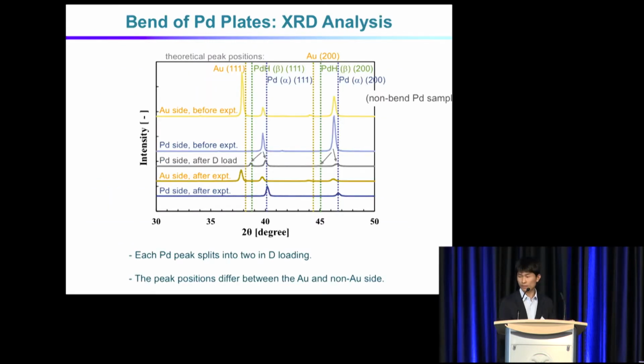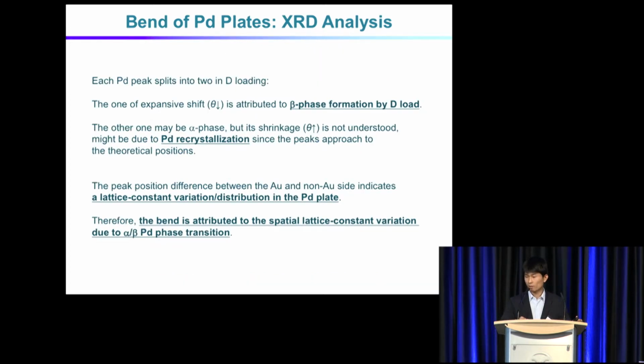And then we analyzed by using X-ray diffraction. The main point was that each peak split into two during deuterium loading, and the peak positions differ between the gold and non-gold side of the plate. The expansive shift, which is represented by the decrease in the diffraction angle, is attributed to beta phase formation by the deuterium loading. And the other one may be alpha phase, but the shrinkage is not understood yet.